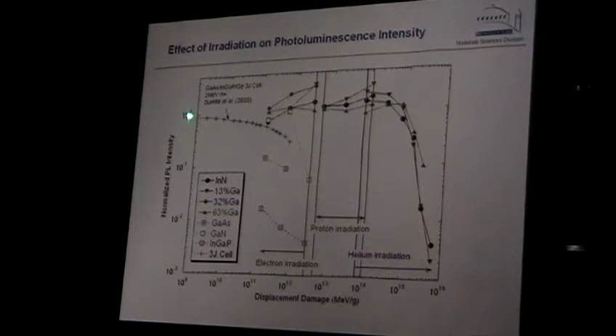If photoluminescence is high, the quality is still good. So you see that photoluminescence in these materials is decreasing very rapidly at low doses. However, if you take gallium indium nitride of different composition, it goes unchanged for quite a while. In fact, surprisingly, in some cases, the quality is improving even with some initial damage. But we understand that finally, when you damage it heavily, everything is destroyed.